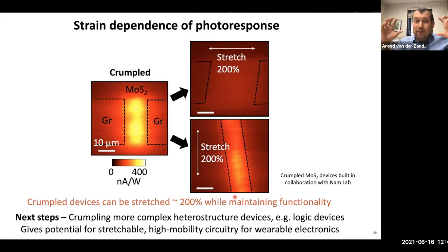And so the reason why this works is first, because each individual material is super thin. And second, because when we stack the layers on top of each other, they can slide a little bit to relieve the strain. And thereby, even under these big deformations, they will relax the strain and still be able to function. Okay.